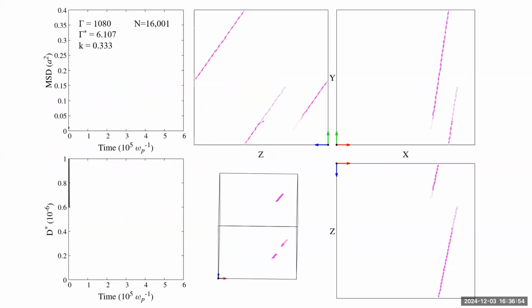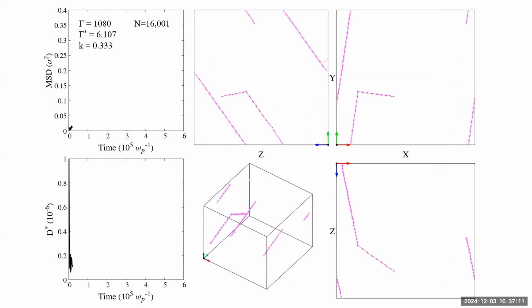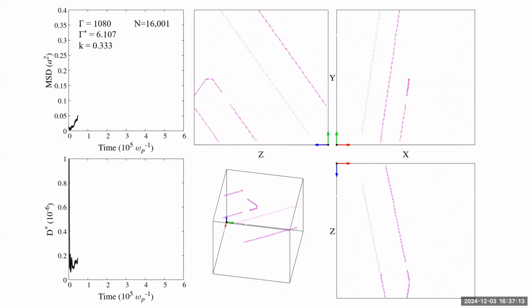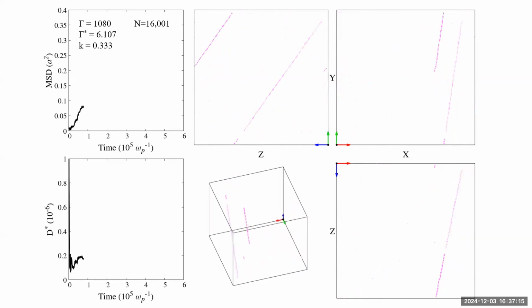What happens if we run a simulation of this? We're significantly colder, at about 1/6 the melting temperature here. The simulations I showed you earlier were very near the melting temperature. And again, you can't tell the vacancies and interstitials apart because they worm their way through like snakes. Notice what happens in this simulation. I'm going to just stop talking and let you take it in for a minute.